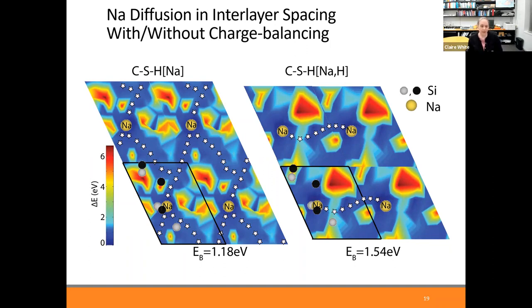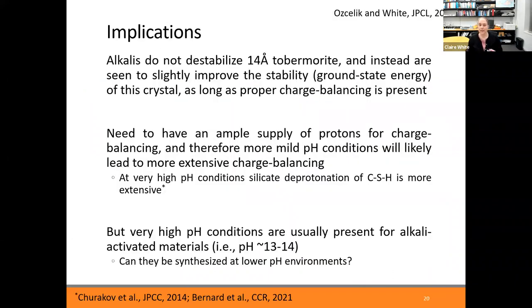Here what I'm showing is just for sodium in the interlayer with and without a hydrogen charge balancing mechanism. Without it, what we find is the barrier to diffusion is 1.18 electron volts. What you can see is the barrier increases when you charge balance using a hydrogen atom. So this is indicating that you can add sodium to the system, so you can have a sodium containing gel.